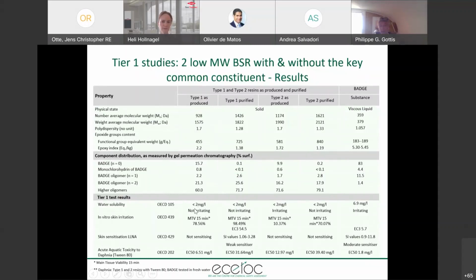BADGE substance is not very, let's say, water soluble, but the polymers, the solid resins, are insoluble by a limit of detection of 2 milligrams per liter. And the overall picture provided by the other test is that BADGE N=0 is not bioavailable, or not to an extent which would manifest the toxicity of BADGE N=0 in the polymers. We, however, have two outliers provided by the purified resins, but these outlier results cannot be explained by, let's say, considerations on the concentration.